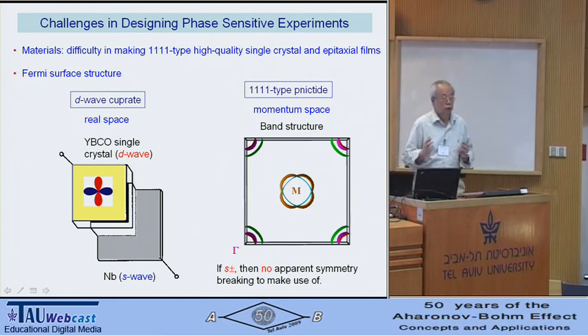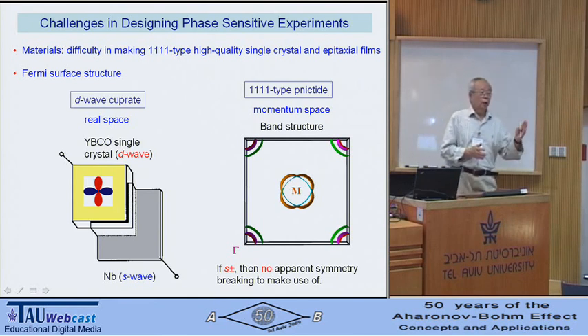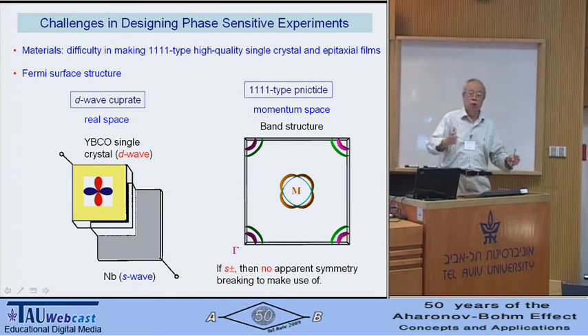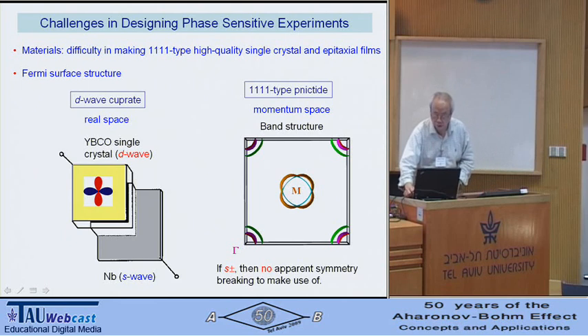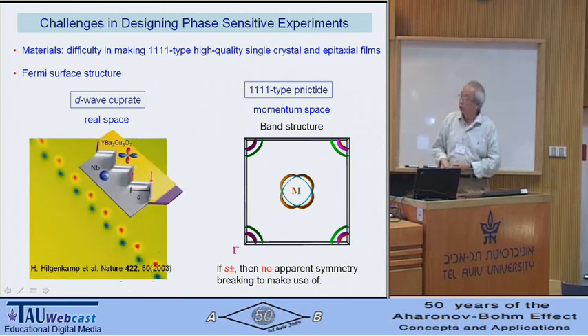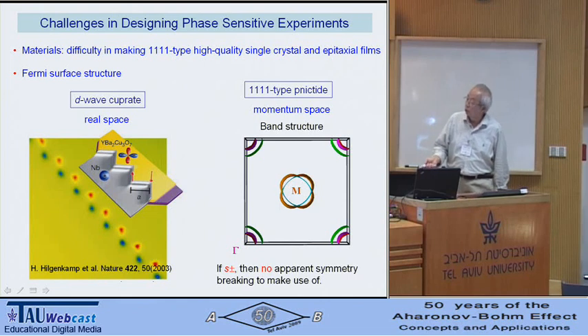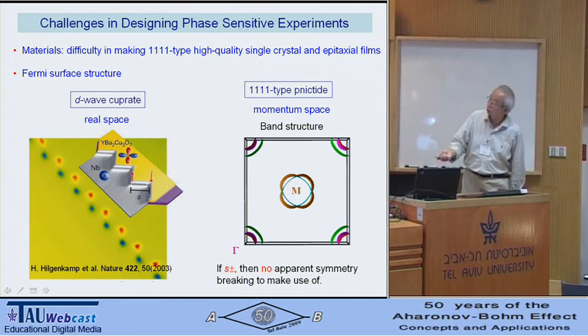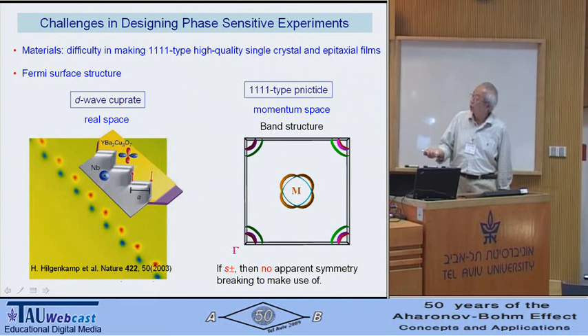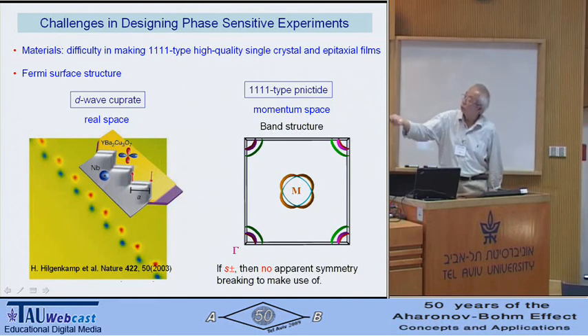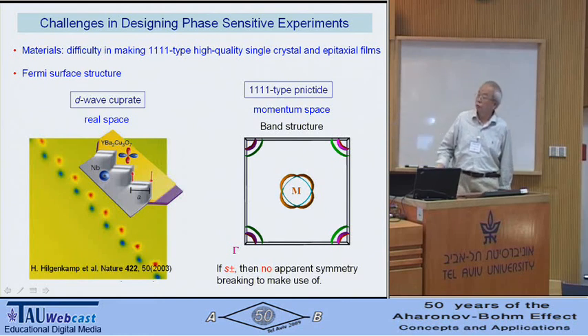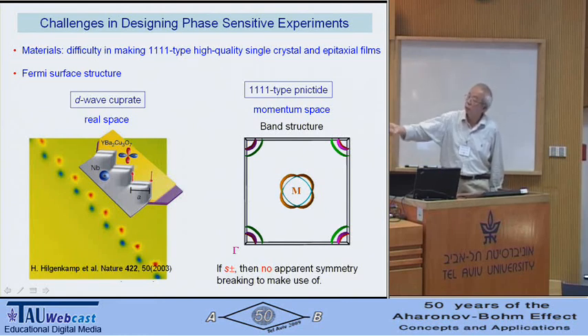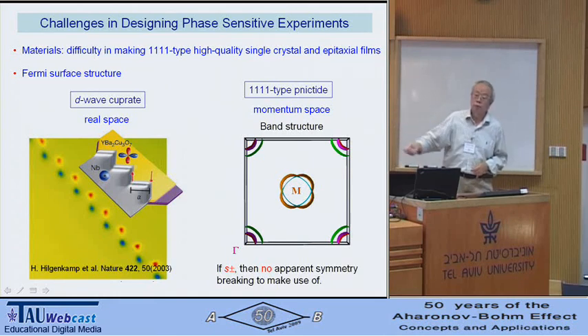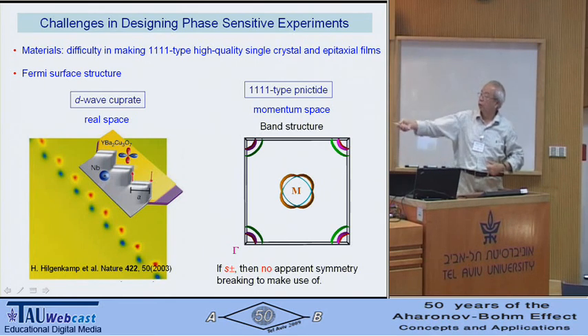So it's relatively easy because there is a one-to-one correspondence from K representation to R representation. So you can design an experiment like this with relative ease. Here is one example, from a paper we published in Nature in 2003. Again there are corner junctions. The corner junction will give you the half-flux quantum effect, and you see it as the zigzag pattern of half-flux quanta. One is up, one is down, because they are antiferromagnetically coupled. So that's what you get.